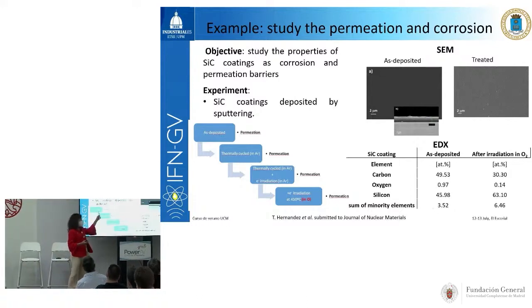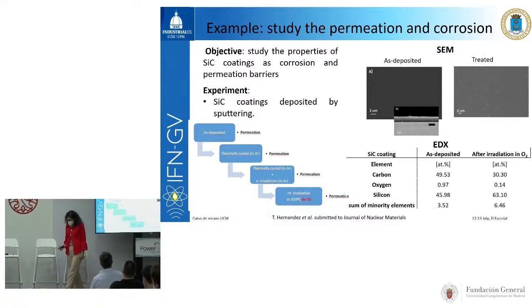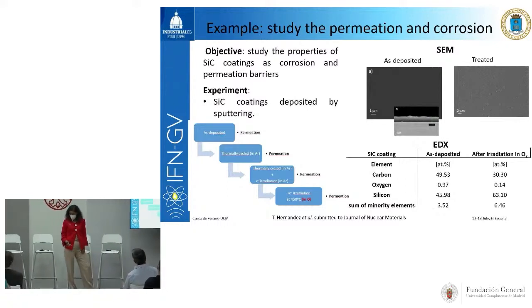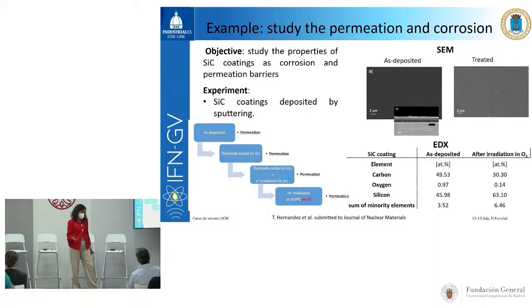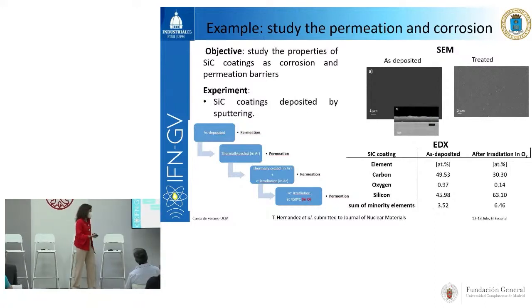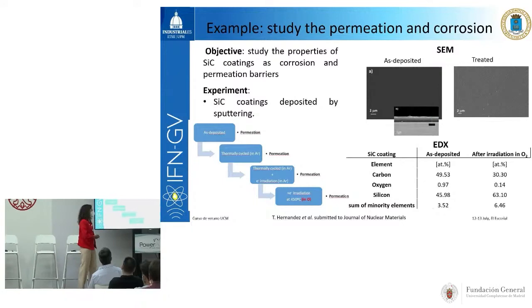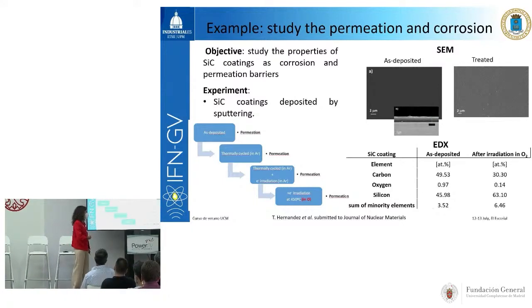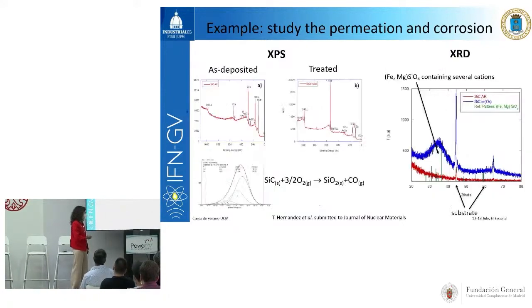So we test as-deposited coatings, we test them thermally cycled and thermally cycled in the presence of electron irradiation, and then we also expose the sample to oxygen, for example, in order to foresee what will happen if we have an accident with oxygen penetrating into the chamber. Okay, and basically here there were different things to be seen.